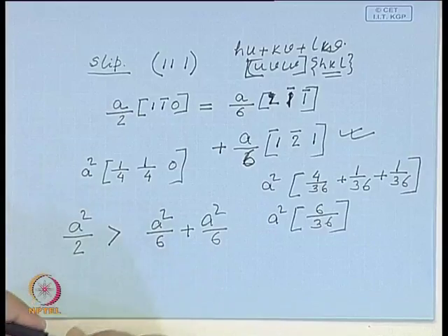So, today in short, we looked at edge and screw dislocation a little more critically. We looked at the movement of edge dislocation. Edge dislocation can move both by glide as well as by climb, whereas screw dislocation can move only by glide. But screw dislocation, as we learnt in the earlier class, can lie on multiple planes.